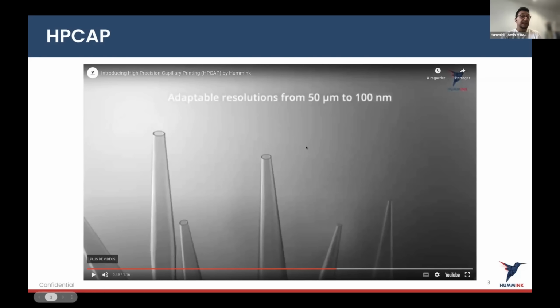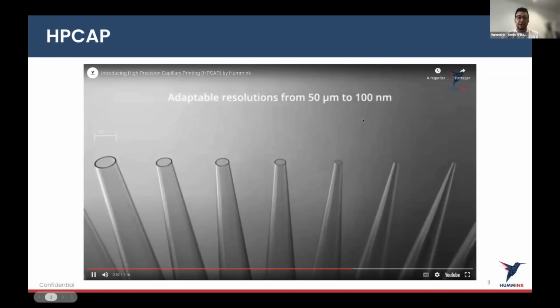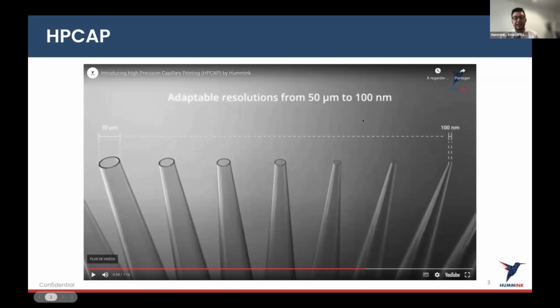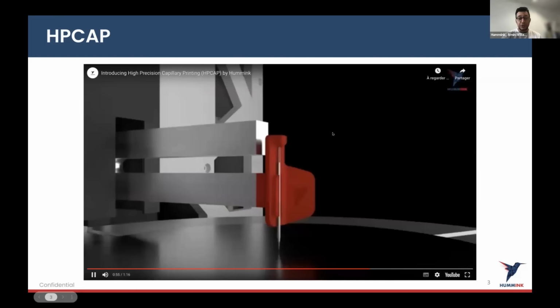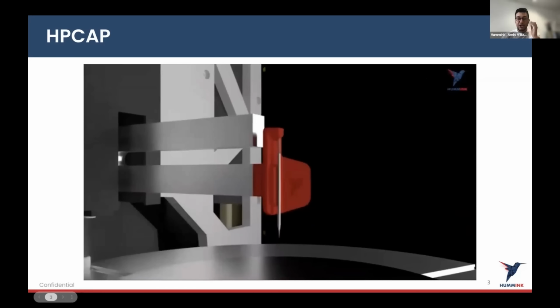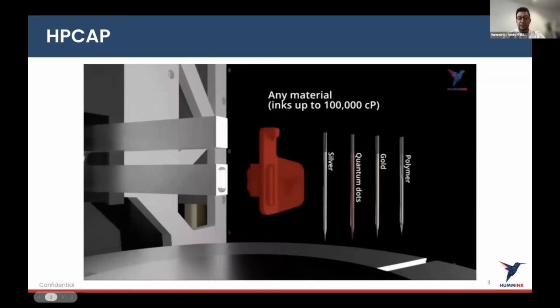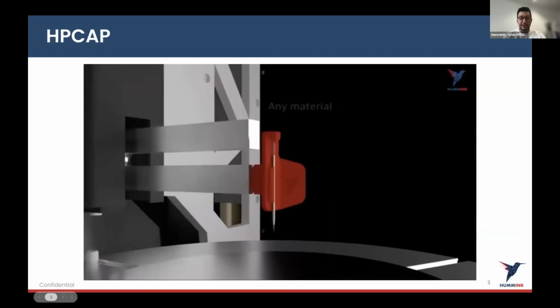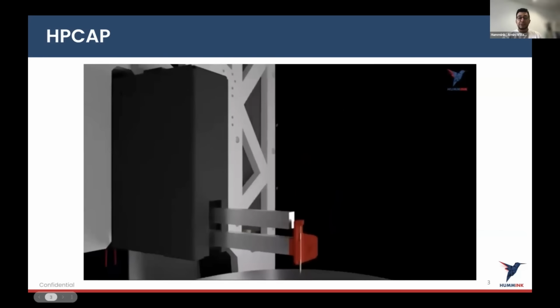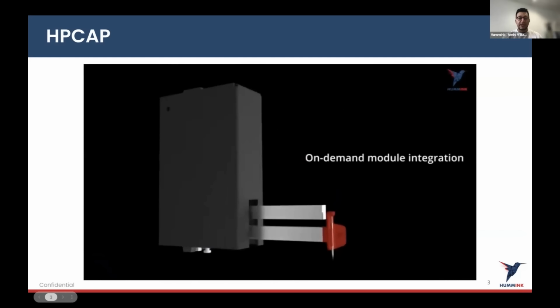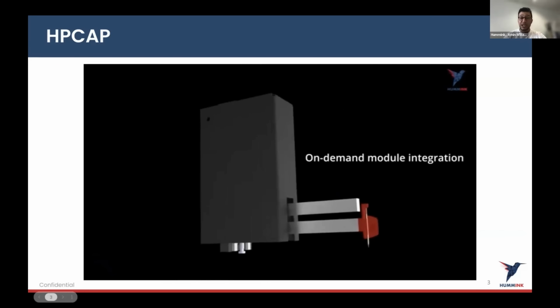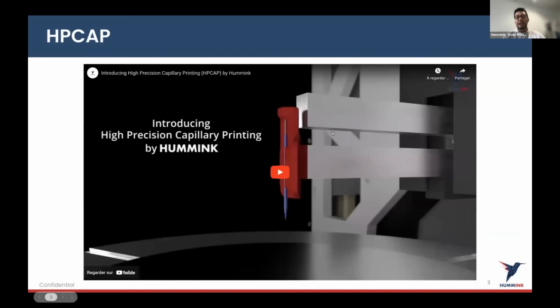At resolutions from 100 nanometers to 50 microns, you can deposit really any ink, and those are the glass tips I mentioned a little before. We pull those glass tips, which creates different diameters, hence different line widths. Once that's done, you can very easily change the tip. This is just a set of examples of what we are able to print. We conceive the technology as an independent printing hand that we hope to integrate in other equipment manufacturers' machines, because we don't manufacture anything ourselves from A to Z. So we need other people's substrates to use our technology.